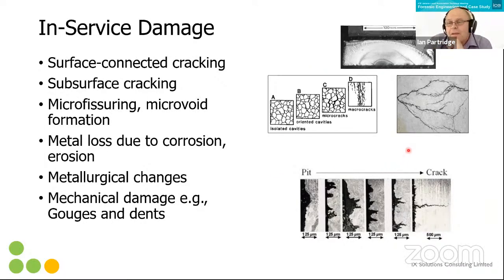It's a good example. The type of cracking shown here is stress corrosion cracking. You need a particular combination of material, environment, and stress generally for stress corrosion cracking to occur. A classic one is chloride stress corrosion cracking, where stainless steels don't like chloride. So stainless steels in seawater is very poor, but they need stress, they need high stresses, yield-like stresses, and you get this crazed-like cracking. Not always crazed cracking, but quite a lot of them are crazed cracking.